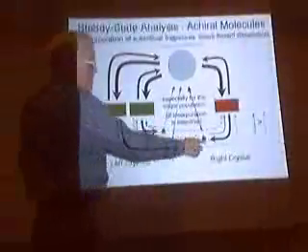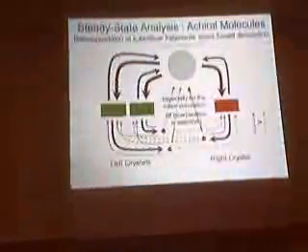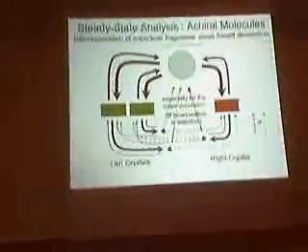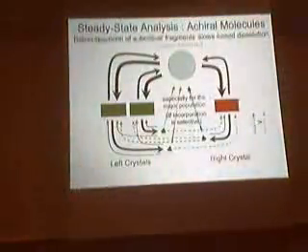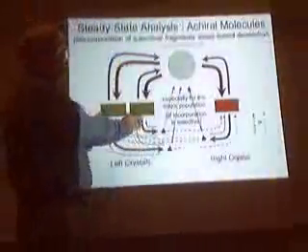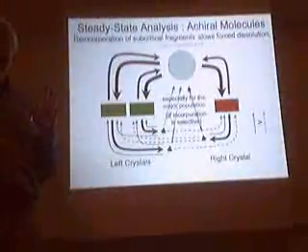Okay, so let's suppose this is only true if the incorporation is selective. This one could go on two, these could each go on another one here. But if you assume that this is bigger than this, if each crystal is selective, chiral subcritical clusters, then it will be true, if incorporation is selective, that there is more slowing down, slower dissolution for the majority crystals. This is really the key feature.